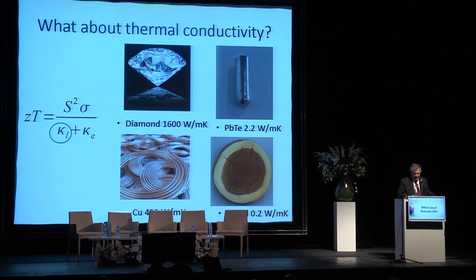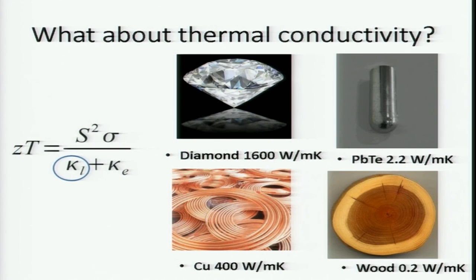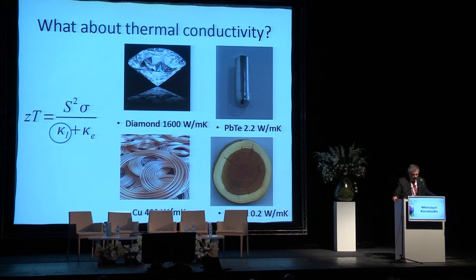That's one key feature. The other is the thermal conductivity. You need very low thermal conductivity for something that will conduct electrons, and that is counterintuitive. Here are examples of thermal conductivity. Diamond is the world's best thermal conductor, and it has 1,600 watts per meter Kelvin thermal conductivity. You don't want diamond, not just for the cost, but the thermal conductivity is too high. On the other hand, copper, another good thermal conductor, has 400 watts per meter Kelvin. You don't want that. Lead telluride, which is a first generation thermoelectric, is about 2.2 watts. Now that's very low. That's closer. And wood is 0.2. So we want something that will conduct electrons well, have high thermal power, but have a thermal conductivity something close to that of wood. And that's what makes this so challenging.